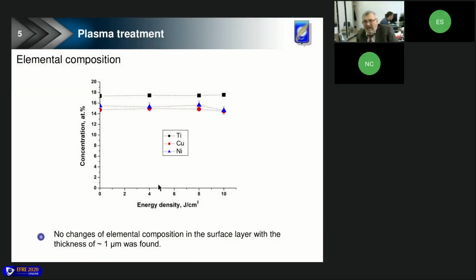The first question that appeared was the redistribution of elements in the surface layer. This kind of phenomenon was observed earlier in certain materials after plasma input. From this figure, you can see that no changes of elemental composition in the surface layer with a thickness of 1 micrometer were found. And 1 micrometer is simply the thickness of the layer analyzed by energy dispersive X-ray analysis. It should be noted that some carbon contamination at the surface was found, but its concentration was not taken into consideration.